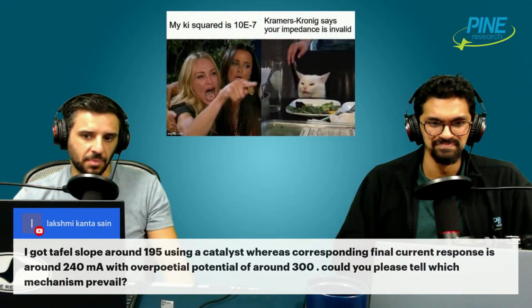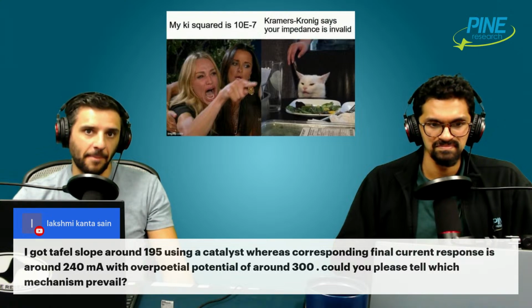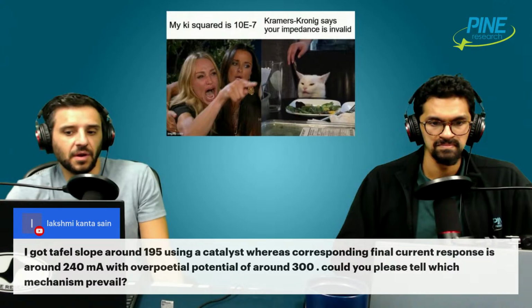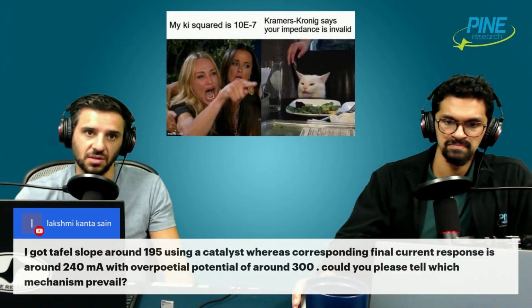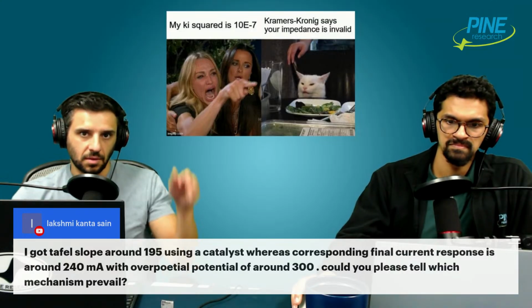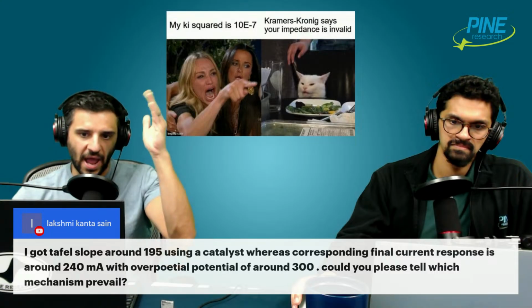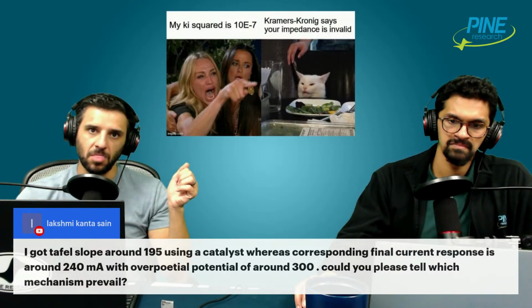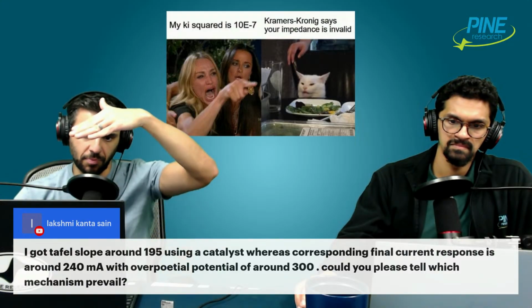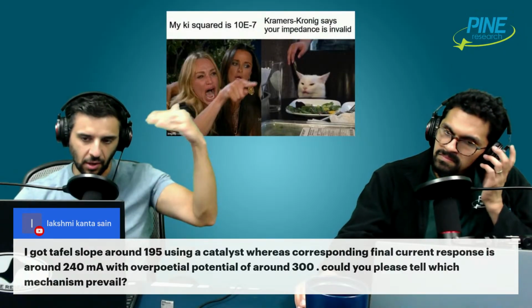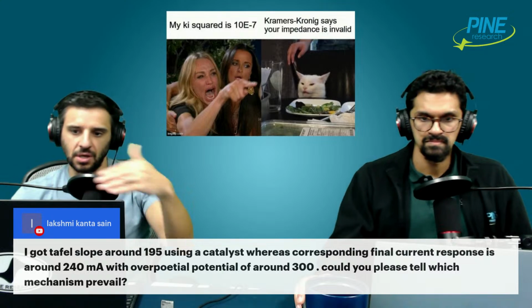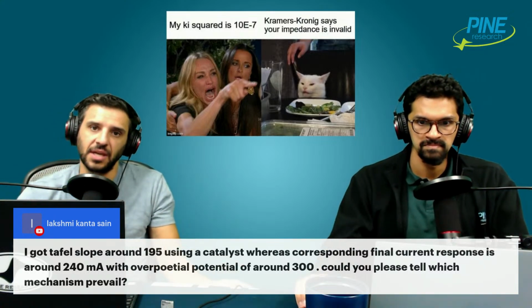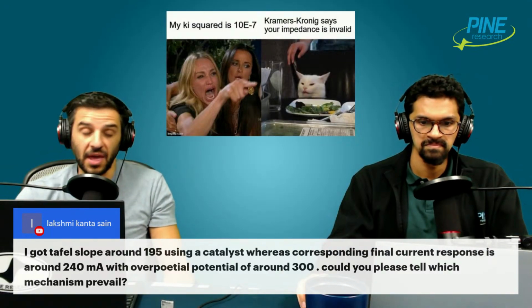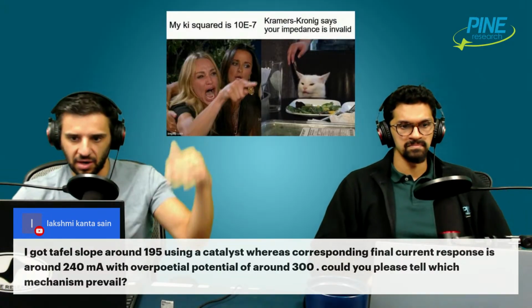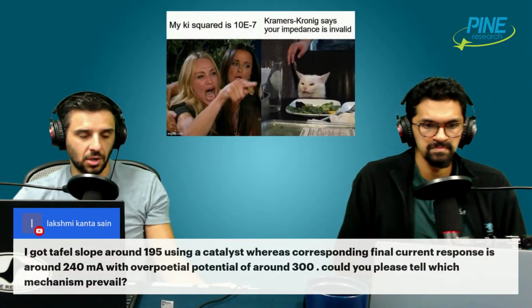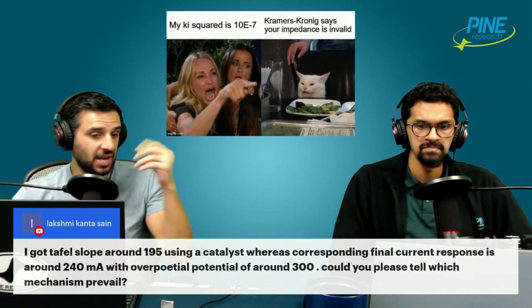But even in the case that you have pure kinetic data, often what happens with a weird looking Tafel slope number is that you've simply used the wrong voltage range over which to take the slope. Because on a Tafel plot, the y-axis is the voltage and the x-axis is the log of current, the range at which you take your slope could be over here, or over here, or over here. Where do you take the slope? Now, if there's a very obvious linear region on your Tafel plot, and it's real Tafel data, see my previous diatribe, then great, you have a Tafel slope. But sometimes it'll be a little curved, or your overpotential might not be big enough.